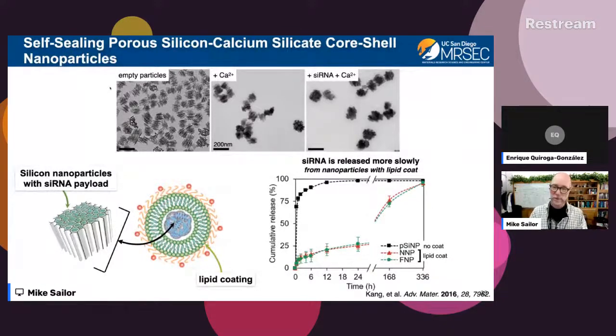We took these nanoparticles and we coated them with a lipid on the outside. And you can see what that does for our drug. Now, the green and the red traces there are using these liposomes or lipid coatings to protect that nanoparticle. When we coat that nanoparticle with this lipid, it dissolves much more slowly and it releases the RNA payload much more slowly. So this pace of release was now appropriate and pretty much a good match for how long we thought our nanoparticles would circulate in the body. And so this chemistry worked perfectly, but we had to add that lipid coating to get it to behave.